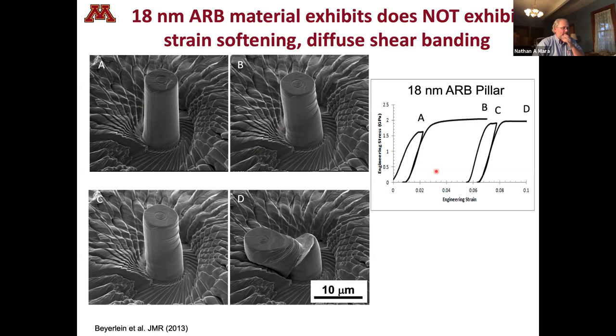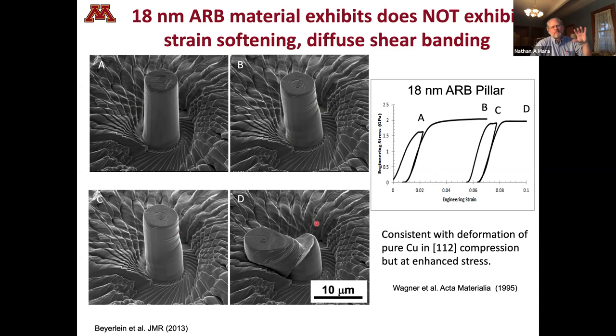And what we found was that it's very consistent with deformation. If you were just to take a pure single crystal of copper, compress it in the same crystallographic direction, so if you were to compress along the 112 direction in copper, very similar kind of behavior, but just at a very much enhanced stress. So all those interfaces are acting as obstacles, but they're really not giving rise to new deformation mechanisms like what we saw with the PVD material.